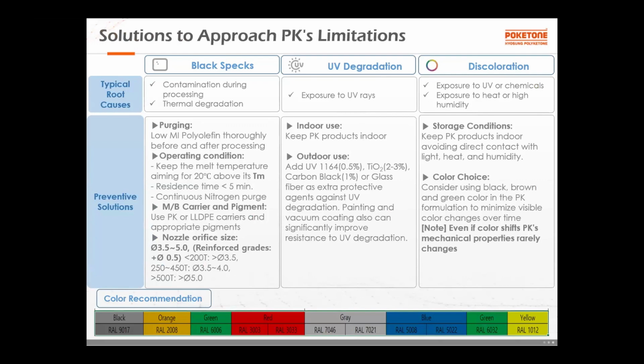Also, we have weakness. So we have 3 weaknesses like the black specks and UV degradation and the discoloration. To improve this black speck, we should keep the melt temperature 20 degrees C above the melt temperature of our polyketone. And also, definitely, if the residence time is not that long, it will be better. And we have to purge nitrogen when you do the injection molding and extrusion molding, then it will be very helpful to reduce the black speck issue.